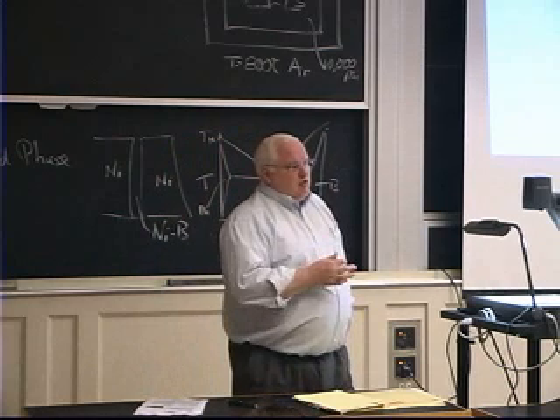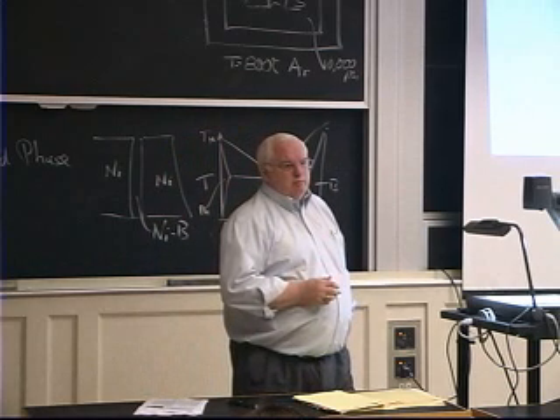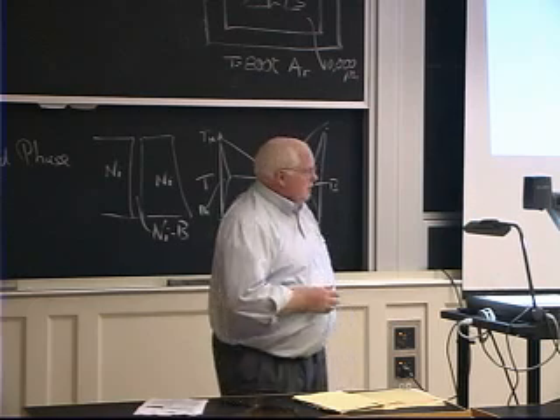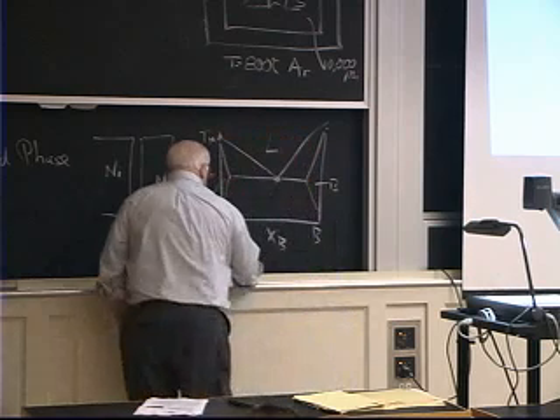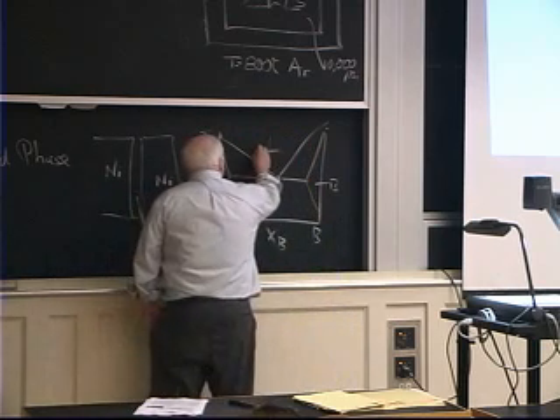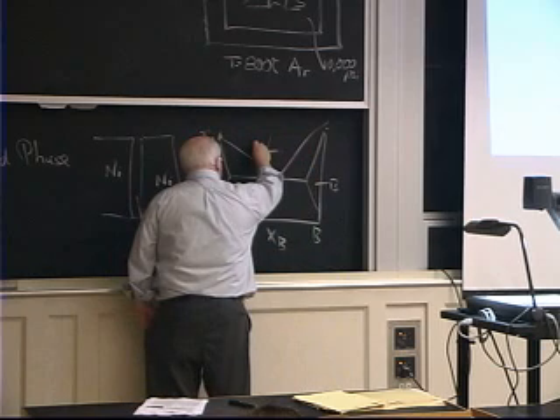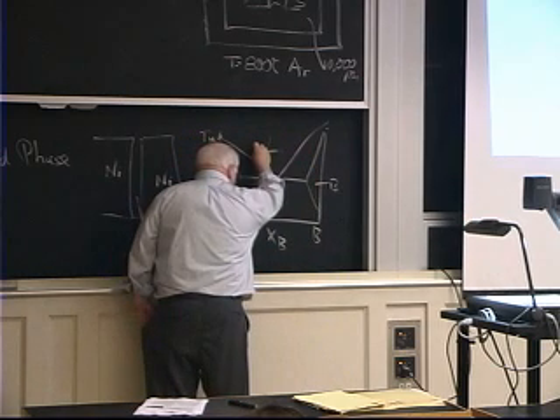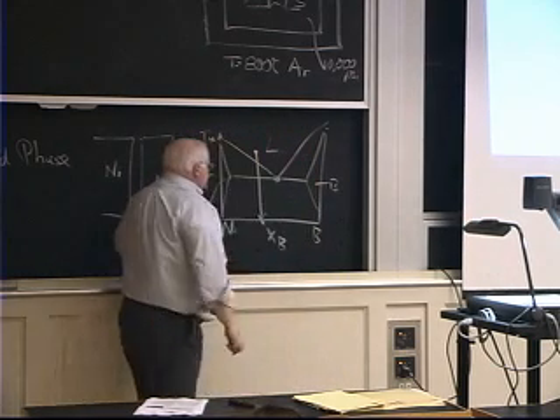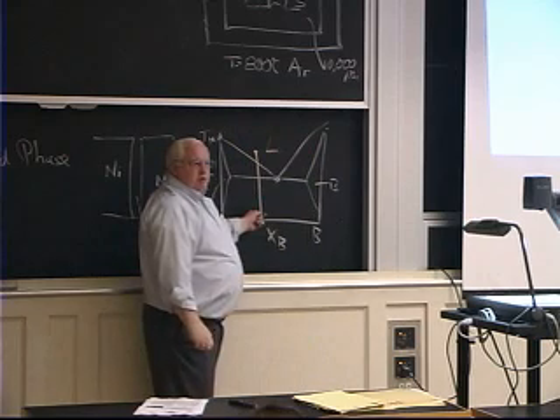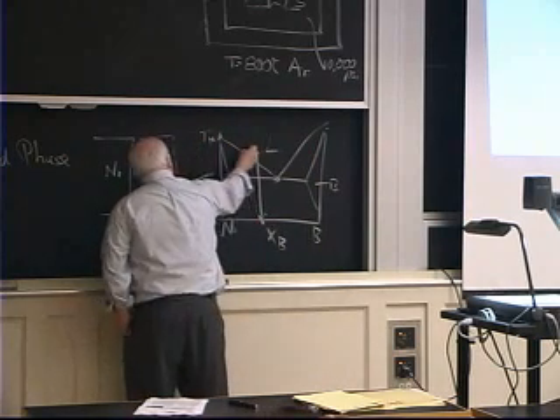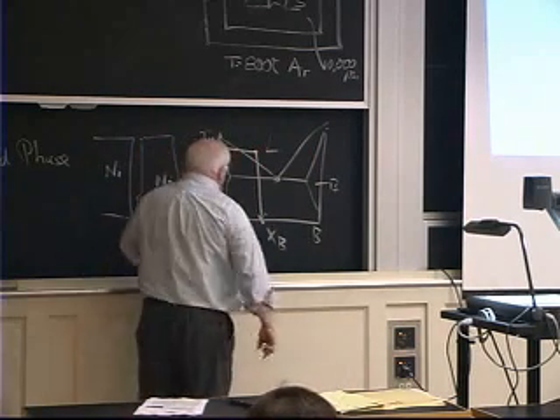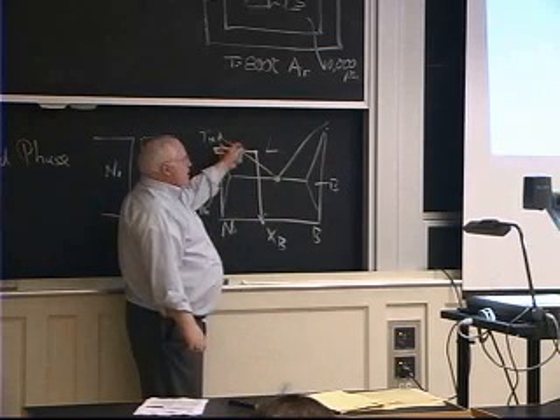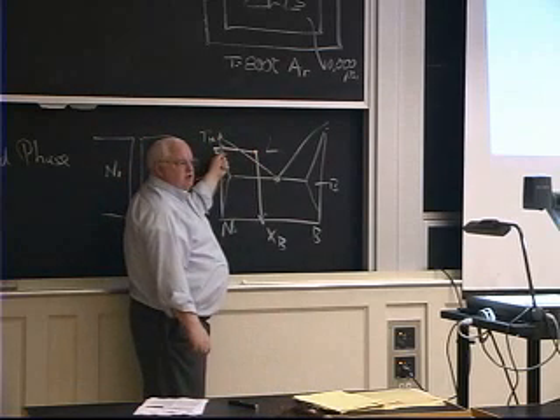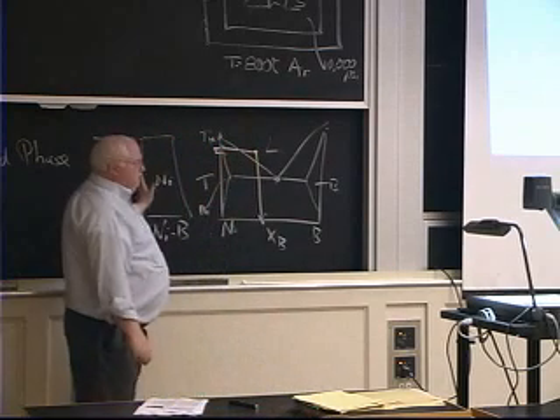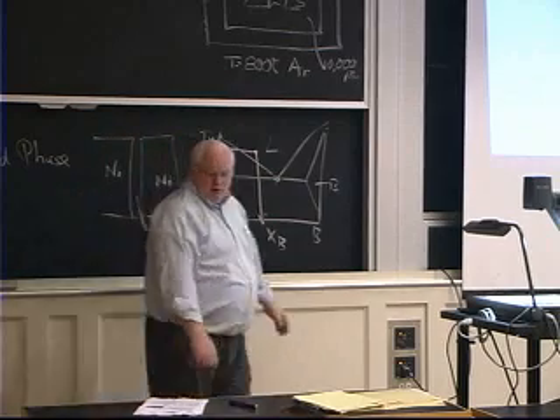It takes it out of the seam, and you freeze the seam. Okay? So it's the same type of phase diagram. And what we're doing is, in regular solidification, I have the same composition, and I just lower the temperature, and I freeze by going down in temperature. In TLP bonding, I keep the same temperature, and I go across the phase diagram, going from the liquid region to the solid region by changing the composition. The boron diffuses away, I change the composition of the center.